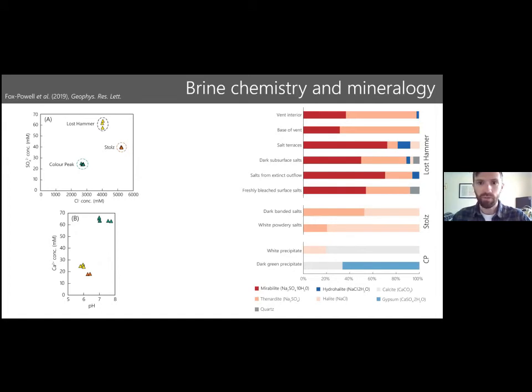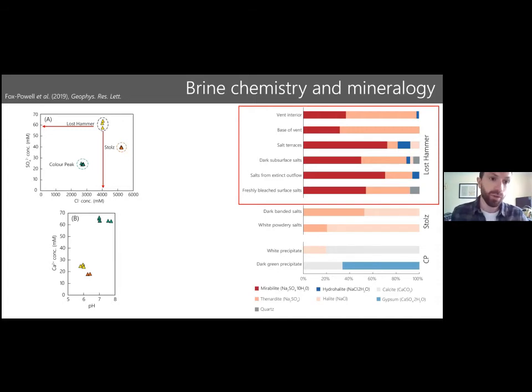We have on the right-hand side the mineral compositions. Don't need to worry about what the specific minerals are, but it's worth pointing out that these are the three springs. You can see just by eye that they're qualitatively very different from each other. At Lost Hammer, we have this red bar and this peach color bar. These are sodium sulfate minerals. But the brine, as you can see on the left-hand side here, is very rich. Its chloride still dominates over sulfate by a couple of orders of magnitude. So we're forming a sulfate-dominated deposit here from a chloride-dominated fluid.